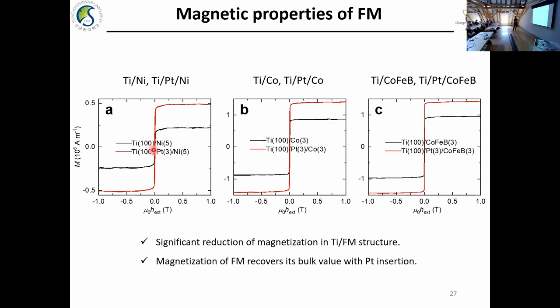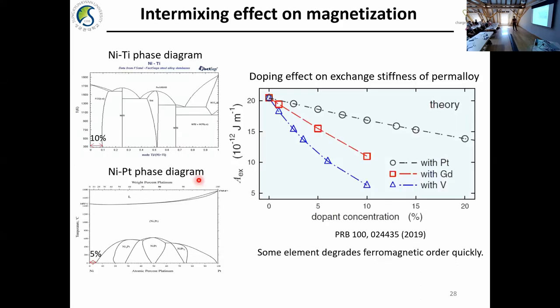When I insert the platinum layer, the magnetization saturation recovers above bulk value. The reason for the magnetization saturation reduction is related to phase diagrams: nickel-titanium has a larger solubility at room temperature, and titanium is known to destroy ferromagnetism easily, whereas platinum does not destroy ferromagnetism even when mixed. For this reason, we use this capping structure to avoid intermixing.